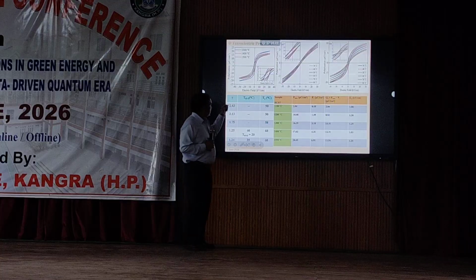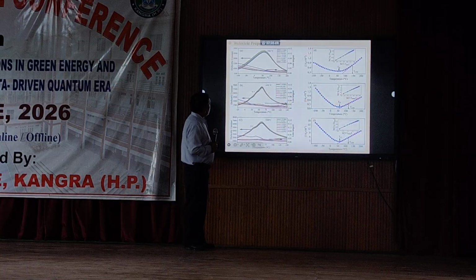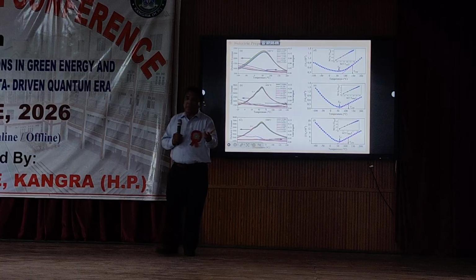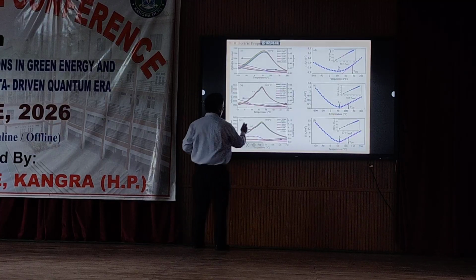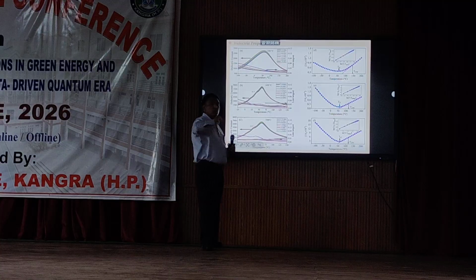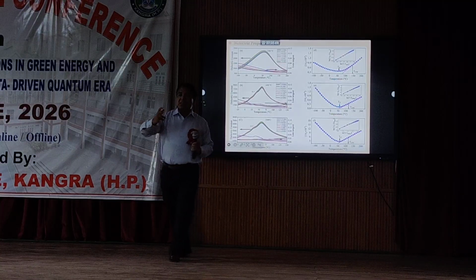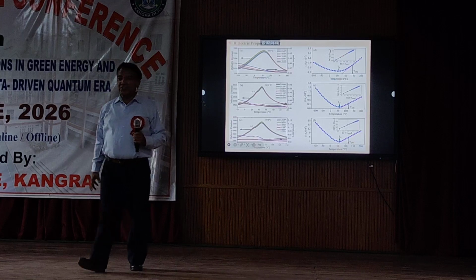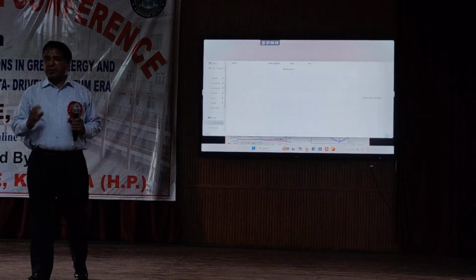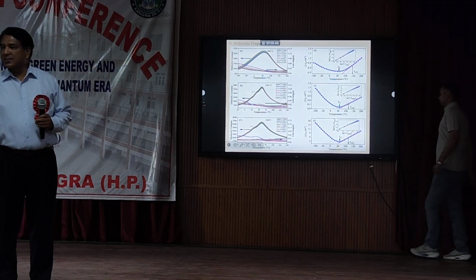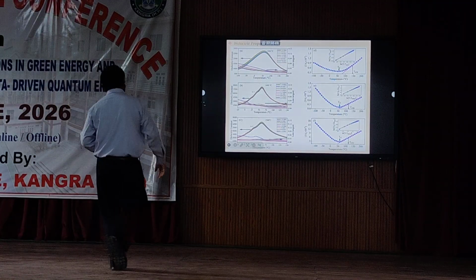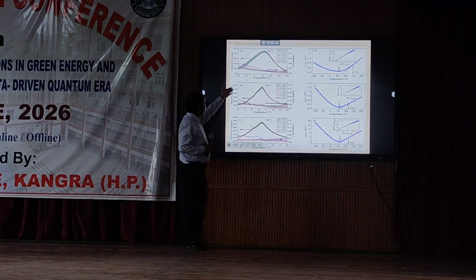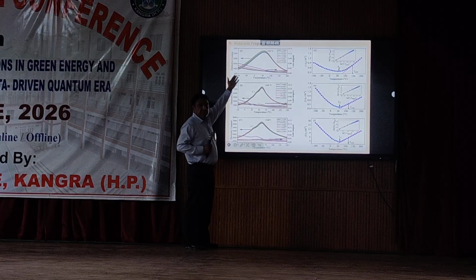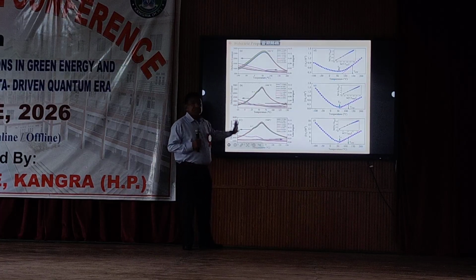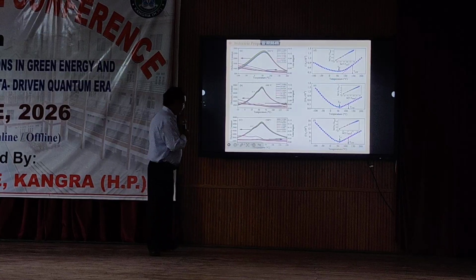So the first anomaly corresponds to rhombohedral to orthorhombic. This anomaly or this anomaly. The second anomaly corresponds to orthorhombic to tetragonal, and the third is tetragonal to cubic, that is the Curie temperature. And in all the cases they are close to room temperature. This simply means the morphotropic phase boundary is very useful in enhancing the polarization. And one can see here a very high dielectric constant, in the 8000 range in these two cases, and below 3000 in the first case, because of the existence of the morphotropic phase boundary.